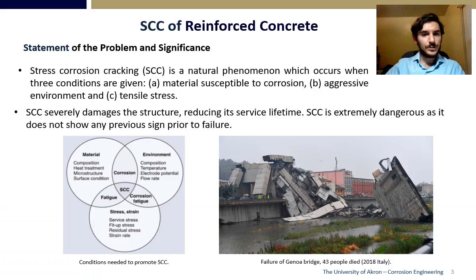Let's start by describing what stress-corrosion cracking is. SCC is a natural phenomenon which occurs when three conditions are given: first, a material susceptible to corrosion; second, an aggressive environment; and third, a tensile stress. SCC severely damages the structure, reducing its service lifetime. However, and more importantly, stress-corrosion cracking is extremely dangerous as it does not show any previous sign prior to failure.